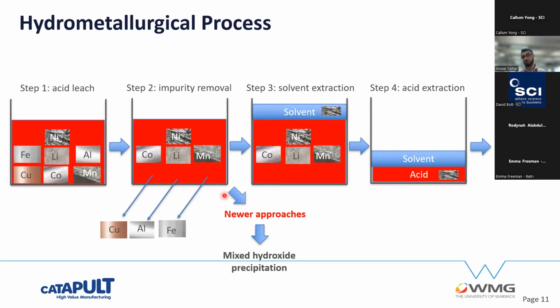So actually what people have done is they've begun to go to newer approaches. They're saying because we're recycling it back into batteries, there's no point separating all these metals into their individual components. Once you take the impurities out, you can get a mixed metal hydroxide. So you can then get a mixed hydroxide precipitate, and then that can go straight back into a battery. Of course, the problem with this is chemistry changes over time, so your process has to be flexible enough to deal with that. But this can seriously reduce the size of the plant that you require, and also the capital investment that you need as well.